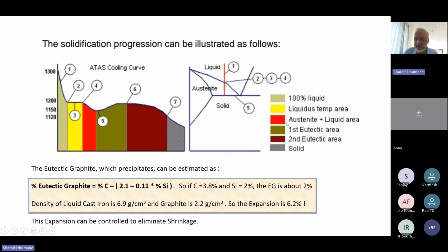So what is that red phase? It is austenite plus liquid. So here it is again that mushy zone. So there is a part of it that is liquid and part of it is austenite solid. Then at point 5 it is completely solid. So that is the first eutectic area. And here now you have your austenite and your cementite or other phases depending upon your chemical composition, whatever it is. Then this is when it comes down below another temperature, and this is called your second eutectic area, and from here onward it becomes completely solid. So these are the phases when the material is cooling down.